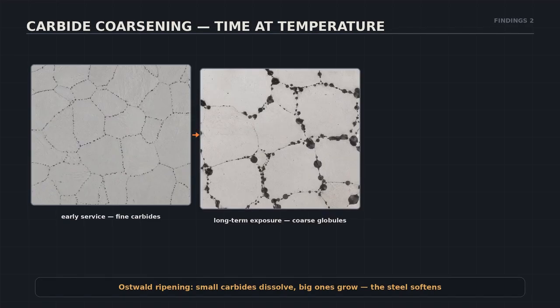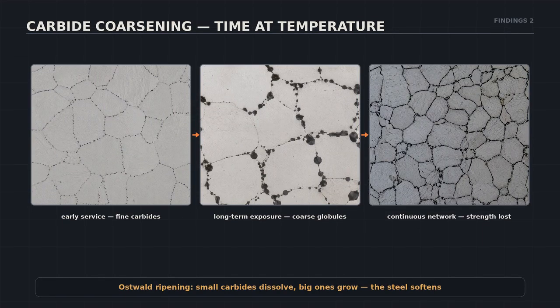Keep running hot, and the carbides evolve. Early in service they're fine and dispersed. With long-term exposure, the small ones dissolve and feed the big ones, Ostwald ripening. The end state is coarse, widely spaced carbides, and the strengthening they provided is gone. The carbides are the steel's temperature diary, and this is what a long, hot chapter looks like.